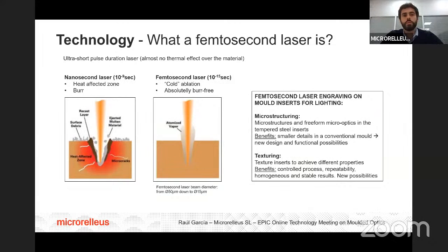A femtosecond laser is an ultra-short pulse duration laser. There is almost no thermal effect over the material. And thanks to this cold ablation, we can achieve micro-engraving, microstructuring, and texturing absolutely burr-free, so absolutely under control. We have here a sketch, a comparison against the nanosecond laser, where there is some thermal effect.